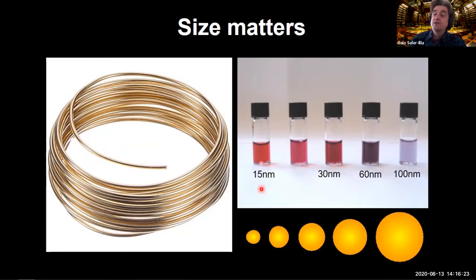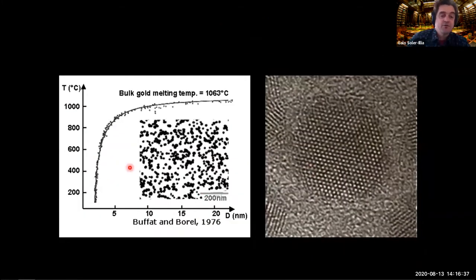It's telling you that when matter is contained in materials that are in the size of nanometers, the intrinsic properties are totally different. And it's not only about the color or about the conductivity. It's also about the melting point. This is a very old experiment in which the melting point of gold is recorded as a function of the size of the particle. This is a very clever experiment made in 1976 by Buffat and Borel. And there is a very clear relationship.